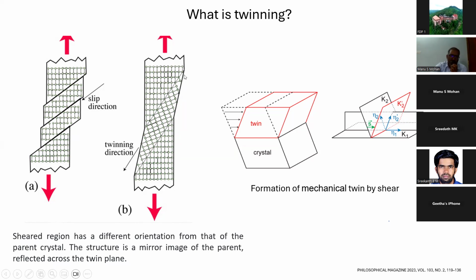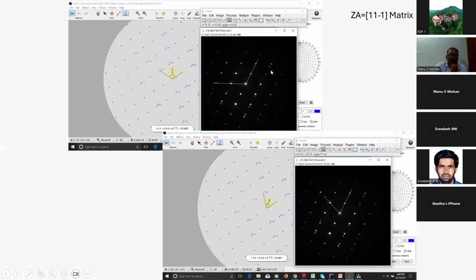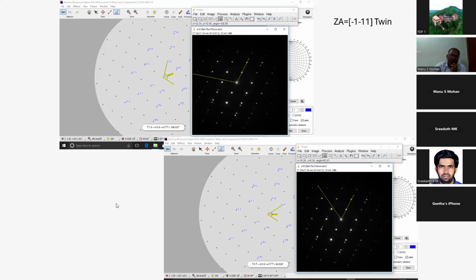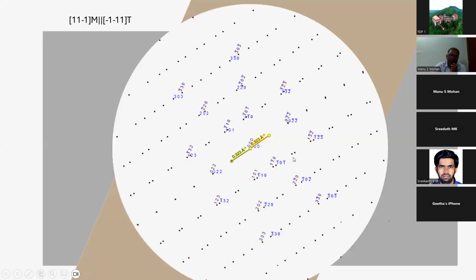You are able to see these twins. So we have simulated the pattern. On the left side you see the simulated pattern, and on the right side you see the image, and we measured the angle. The indexing itself is not very complicated, but you have to verify it by simulating the pattern using 3 parameters - one is the lattice parameter, the other is the space group, and the other is the atomic coordinates. You have to simulate it and measure the coordinates. Finally, this is the twin spot, the diffraction pattern, the simulated TEM diffraction pattern, which I overlapped and matched.